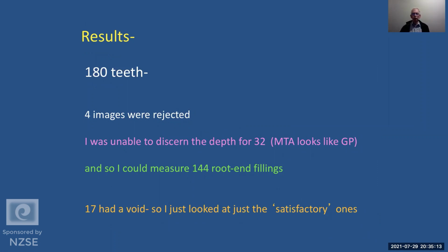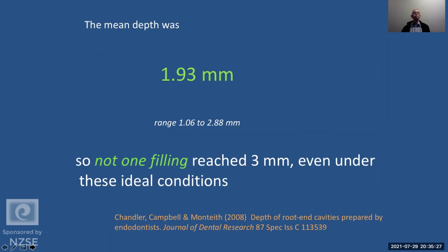So I could measure 144 root end fillings, which is a good number. 17 of them had a void, a gap between the GP, so I didn't know if they'd been adequately filled. So those ones I rejected. And the mean depth was 1.93 millimeters, and the range of cavity depths was 1.06 to 2.88. So not one of those fillings reached 3 millimeters. So the endodontists are given a 3 millimeter cutting tip, and none of them managed to do a filling that's 3 millimeters deep, even under ideal conditions.